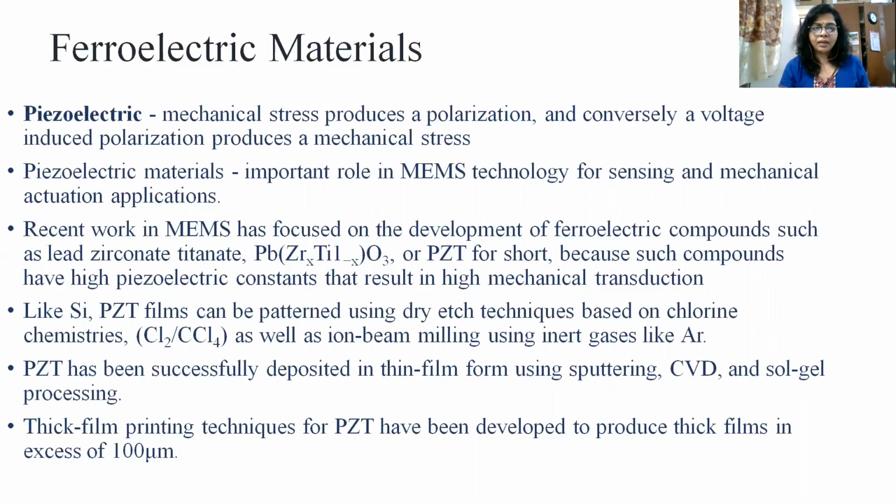transduction. Like silicon, PZT films can be patterned using dry etching technique based on chlorine chemistries. PZT has been successfully deposited in thin film form using sputtering, HFCVD, sol gel process and also PLD technique. Thick film printed technology of PZT has been developed to produce thick film in excess of 100 micrometers.